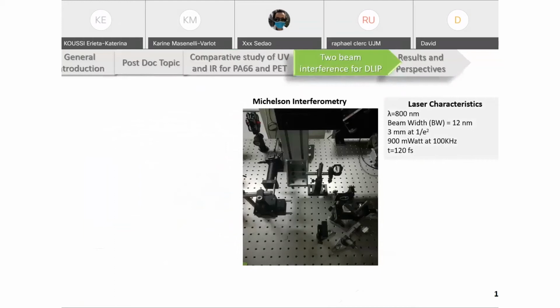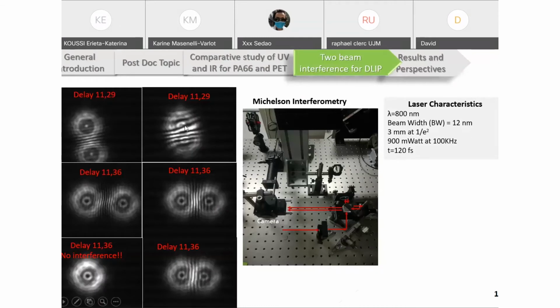And here you can see the experimental setup and the optical path followed. After the beam splitter, the recombined beam ends at a camera where we have found all these interfringes, the patterns, and the images of these fringes are illustrated at different positions of the beams. We can observe that the pattern changes depending on the beam's position, a fact that can allow us to create patterns with exotic configurations. The coherence length of the arms between the beam splitter was extremely delicate, equal to 0.7 millimeters, and we could easily lose the interference pattern.